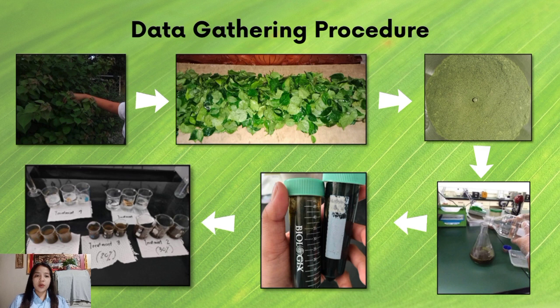The figure shows the flow of experimental procedure that will be accomplished for this study. Approximately 3,000 grams of fresh Bougainvillea spectabilis leaf will be collected around the vicinity of Bungabon, Nueva Ecija. After the collection, the sample will undergo air drying for a continuous 7 days. After 7 days, the sample will be ground using a grinder and soaked in ethanol for 2 days. The solution will undergo rotary evaporation to separate the ethanol from the solution. With this, only essential phenolic compounds or phytochemicals of Bougainvillea spectabilis leaf will remain in the crude extract.